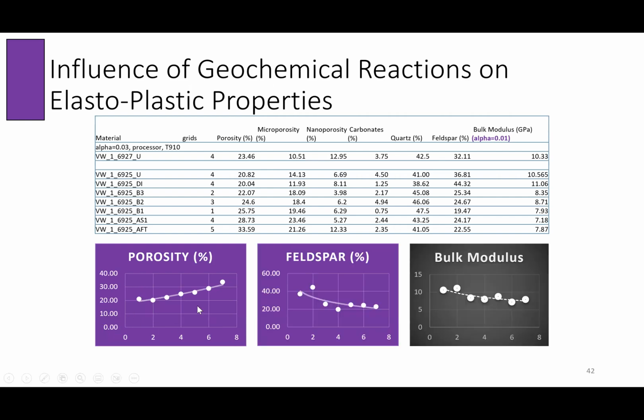So for different kinds of systems, and again, these conditions represent lower, simpler chemistry and then more complex chemistry. And also we have room temperature versus, at the end, high temperature and high pressure with CO2 saturated brine. So when we go from unaltered to complex chemistry and high temperature and high pressure, then we increase the porosity, we decrease the fraction of feldspar, and we decrease the bulk modulus. So because of geochemical reaction, we have microstructural changes, we have compositional changes, we have mineral dissolution reaction, and this is going to lead to a reduction in the bulk modulus.